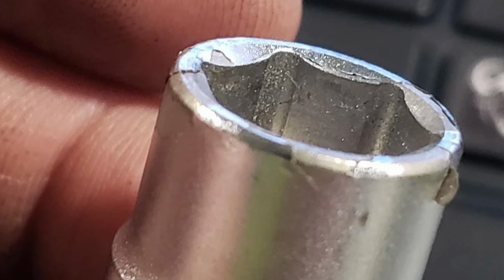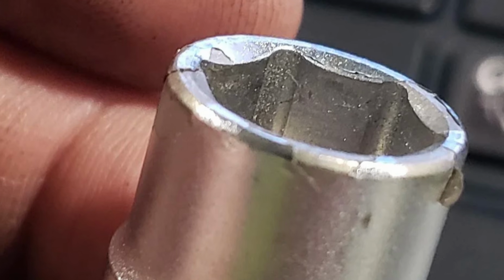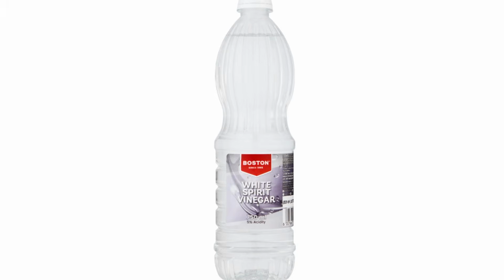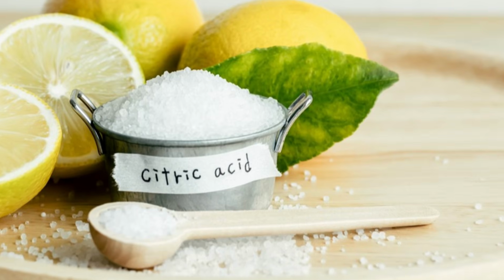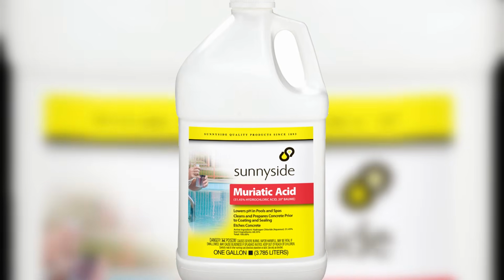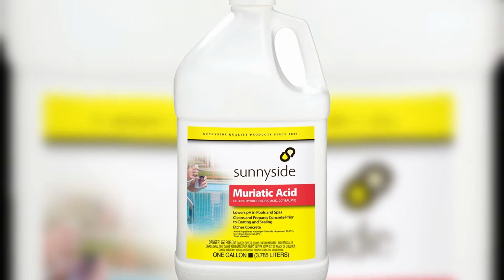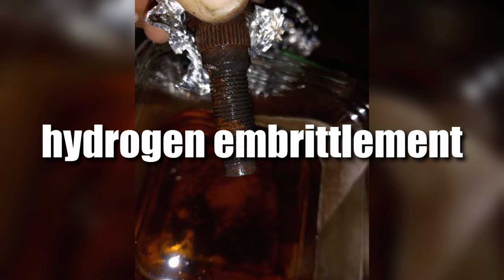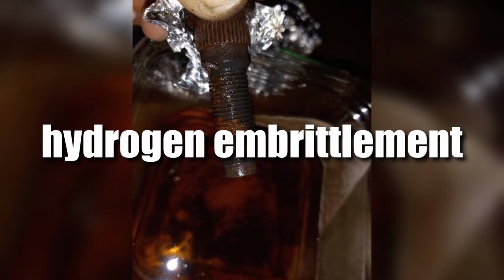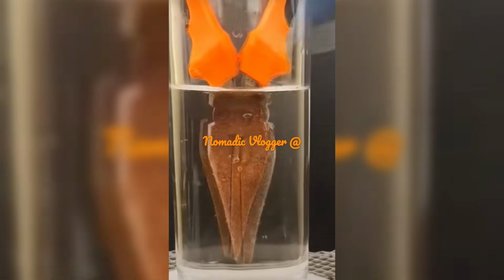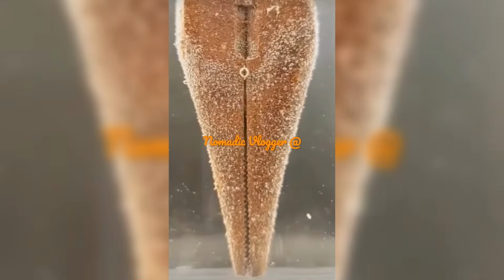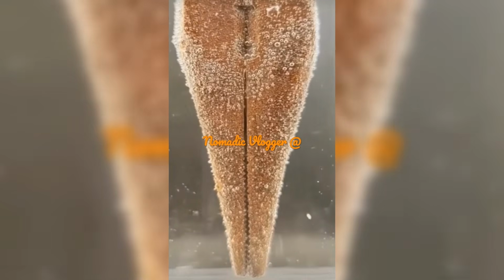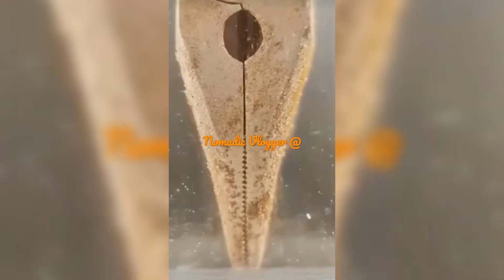When that rust appears, the instinct for most people is to reach for an acid bath. White vinegar, citric acid, muriatic acid, and yes, those acids will dissolve the iron oxide. But they will also trigger a process called hydrogen embrittlement that can permanently destroy the structural integrity of your tool steel. You have to understand that when high-strength steel is submerged in an acidic solution, the acid reacts with the metal surface and generates free atomic hydrogen.